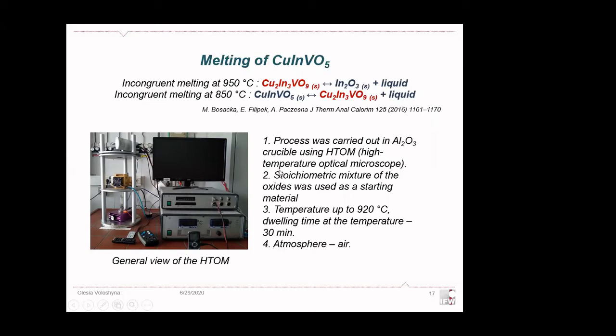stoichiometry. So the process was carried out in a high temperature optical microscope. The alumina crucible was placed in a quartz tube here. Then it was moved up to this chamber, which works just similar to the floating zone furnace. There we have the lamps and the mirrors to create the melting zone. Here we have the camera to observe the process, and we receive a picture on the computer. So the process was carried out in air atmosphere. The temperature and the dwelling time you can see on